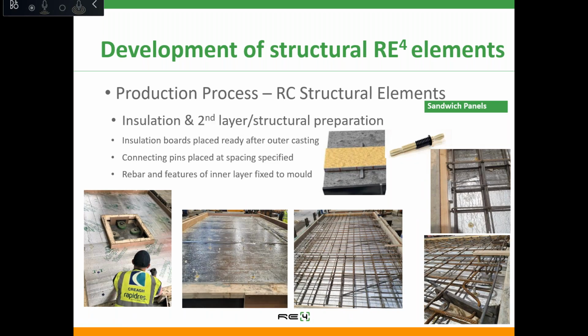When casting sandwich panels, because they have 2 layers of concrete with an insulation board in between, there are extra steps in the production process, which I'm going to show here and in the next slide. So after casting the outer layer of the sandwich panel, we have to place the insulation boards with the fresh concrete in place, so the connecting pins that will link both layers can be placed into the fresh concrete of the outer face.